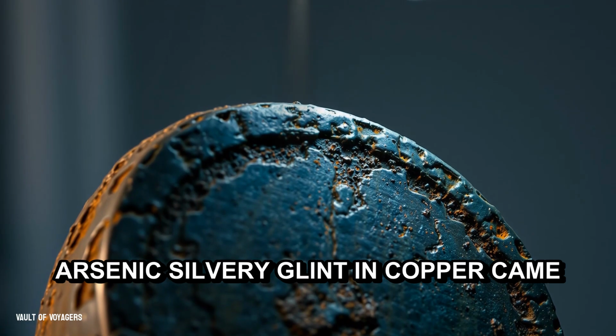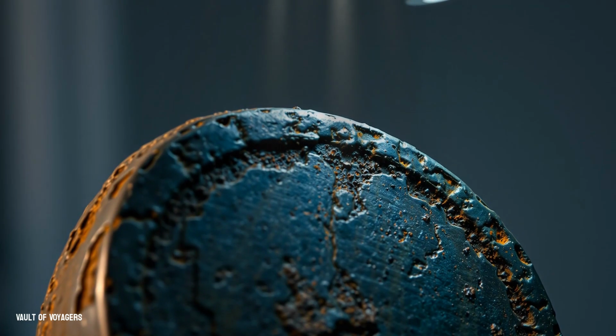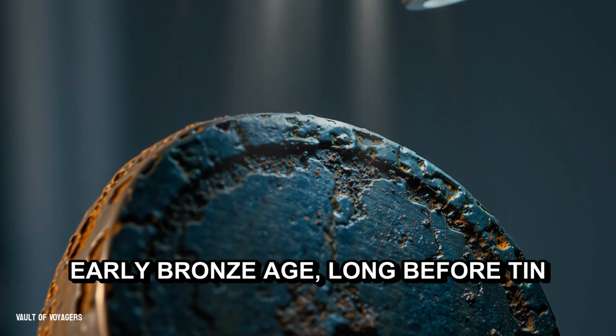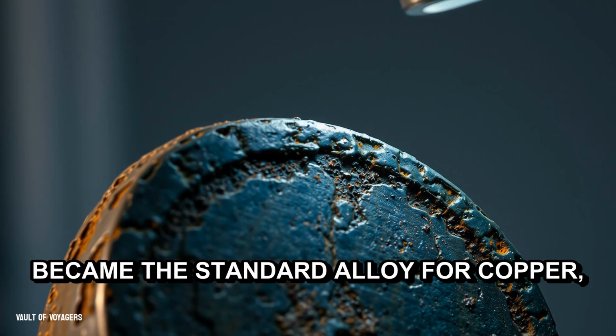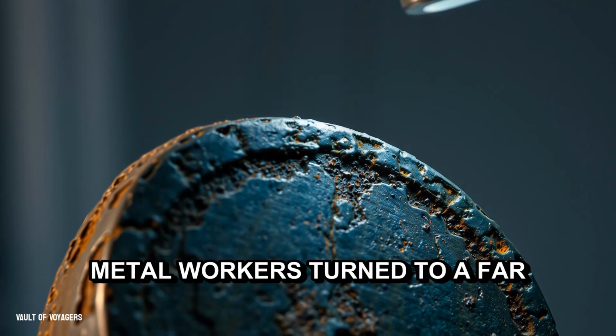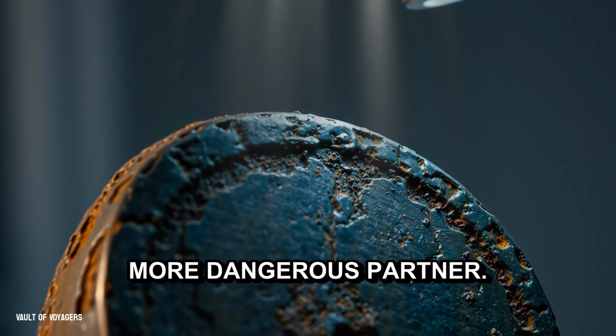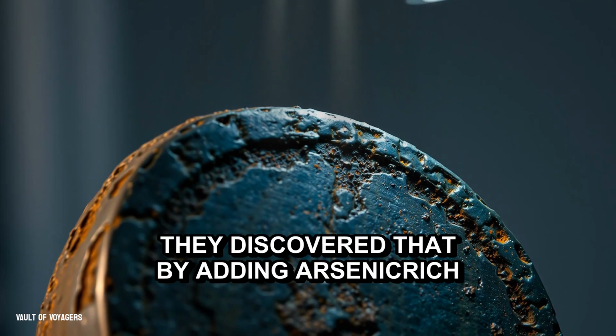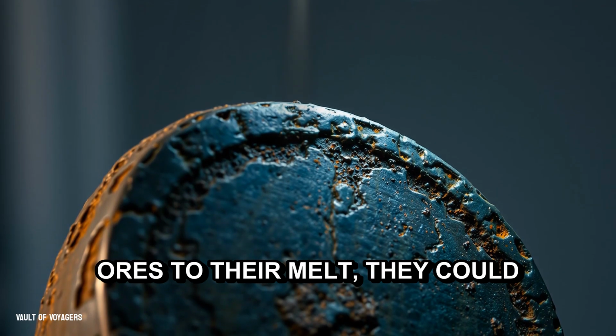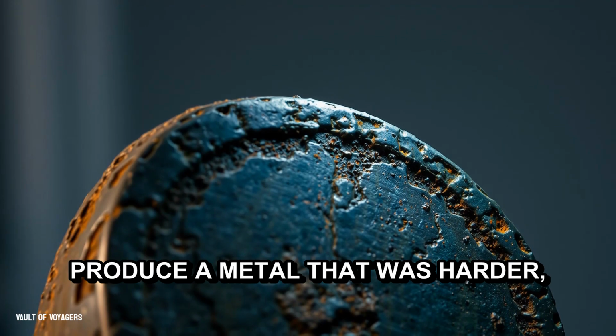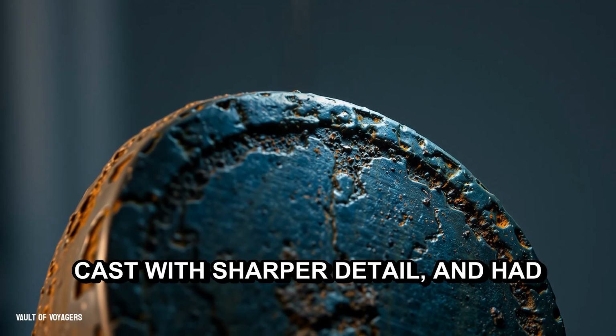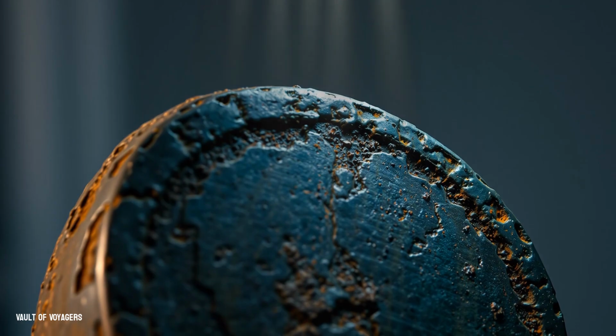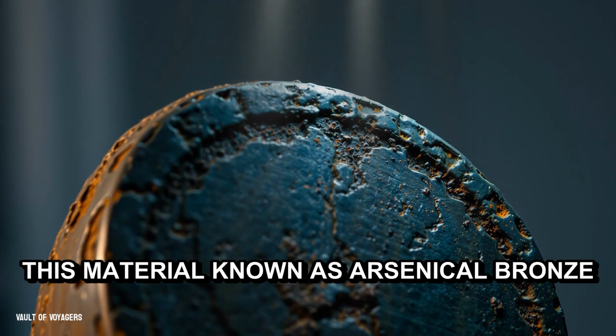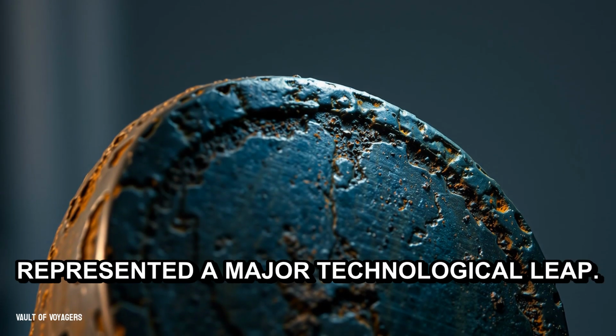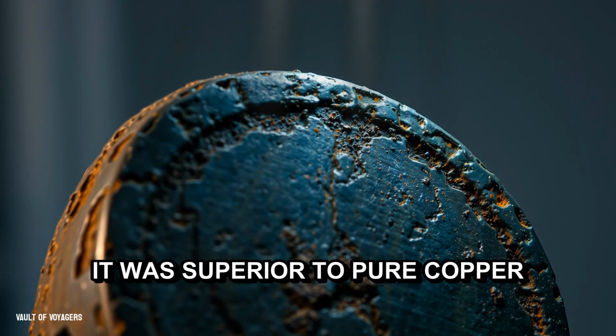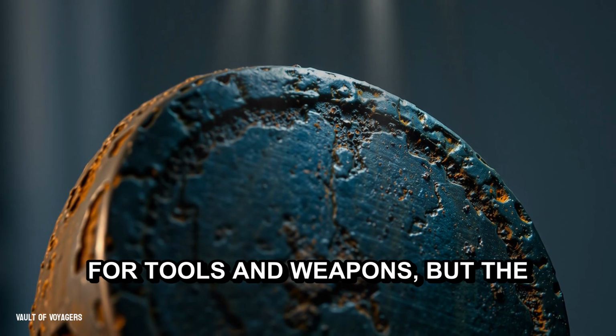Arsenic's silvery glint in copper came at a terrible price. In the smelting pits of the early Bronze Age, long before tin became the standard alloy for copper, metalworkers turned to a far more dangerous partner. They discovered that by adding arsenic-rich ores to their melt, they could produce a metal that was harder, cast with sharper detail, and had a pleasing, pale sheen. This material, known as arsenical bronze, represented a major technological leap. It was superior to pure copper in almost every way that mattered for tools and weapons.